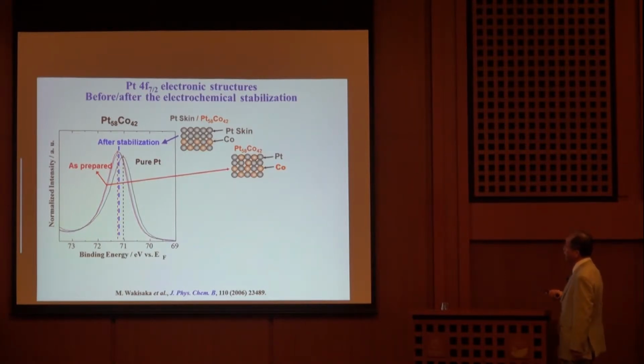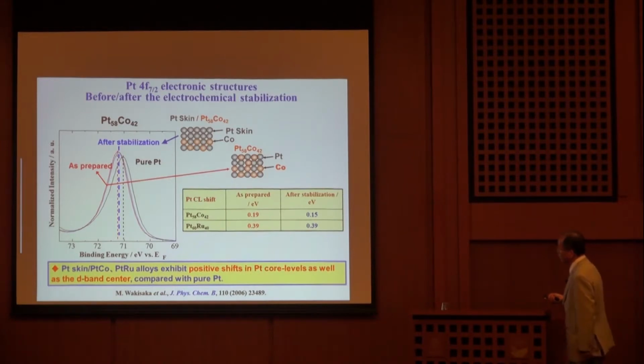And after electrochemical annealing, we observed a very small shift of the binding energy at the skin layer surface. So platinum skin on the alloy surface exhibits a positive shift in the platinum core level as well as the D-band center compared with pure platinum. Particularly for the stable platinum cobalt alloy, we observed almost no change of the core level.